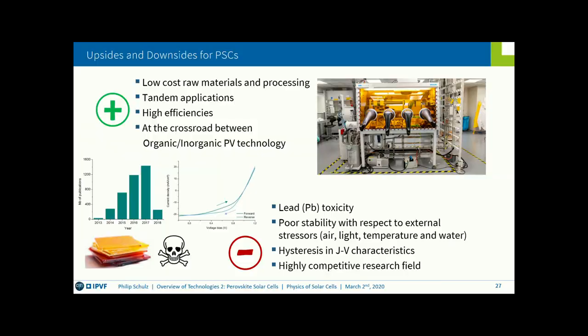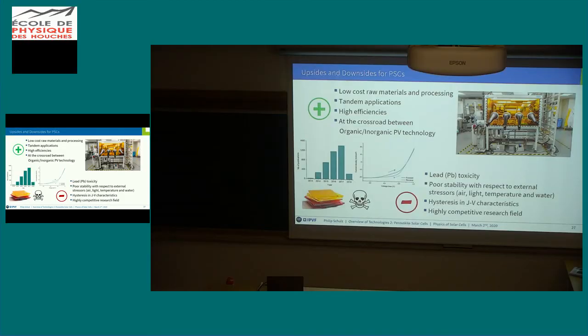Now, in order to summarize this a little bit, what are the upsides and downsides? So yeah, this is another one that I changed a little bit, but the content is more or less the same. We have on the plus side the low cost of the raw materials and the processing. You can integrate perovskites quite easily in tandem applications with silicon, with CIGS, also perovskite tandems, and you get very easily high efficiency. It's at the crossroad between organic and inorganic PV technology, which opens it up to a lot of different processing routes. Then on the minus side, lead is toxic, as I said already. It shows some poor stability with respect to external stressors that are air, light, temperature, and water. So not the ideal case for a device that you want to put onto your roof.